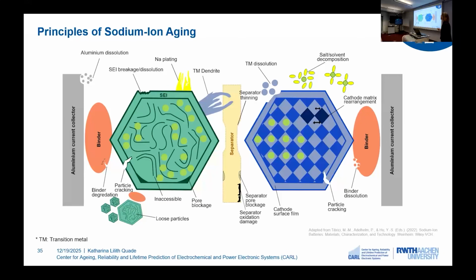However, I will include these and let's focus on the aging of anode and cathode. So on the anode side, we can see the SEI, and aging is mainly driven by the formation, growth, and also breakage of this passivating layer that binds cyclable sodium. And this growth is especially accelerated due to the repeated sodiation and desodiation in the anode. And this can lead to a so-called breathing of the cell. This can then lead to particle cracking, as we can see here. And we can also see that this exposes the electrode surface to the electrolyte again, and this can then lead to electrode-electrolyte reactions. Here we can also see that the SEI can break and dissolve.